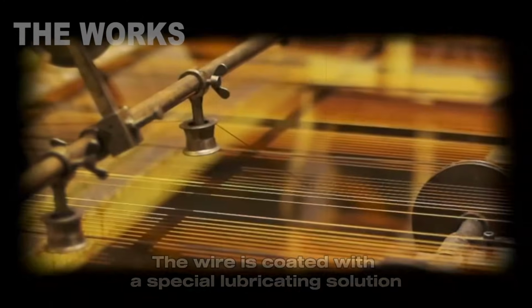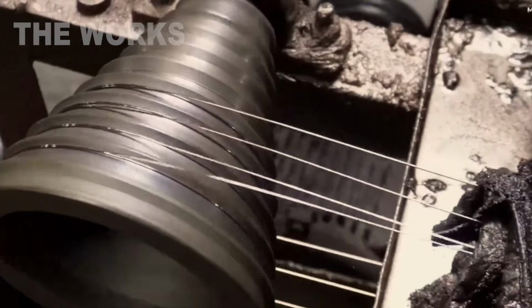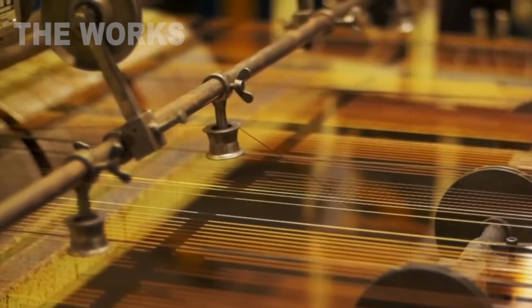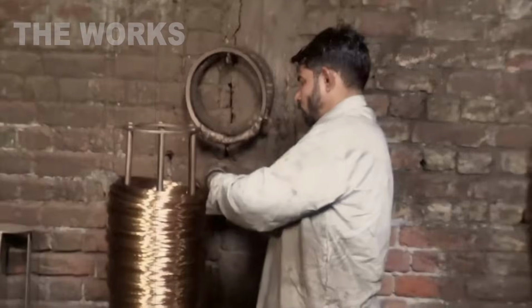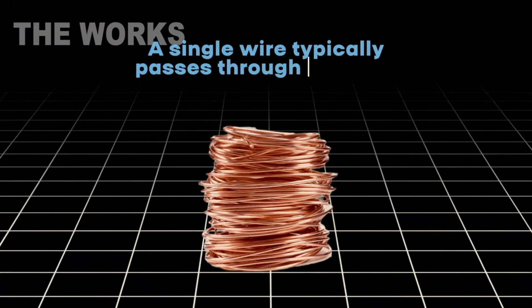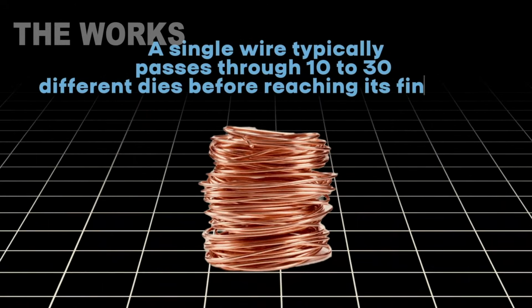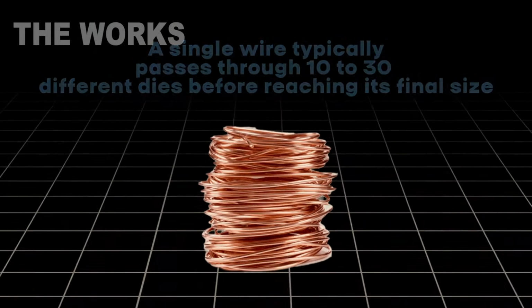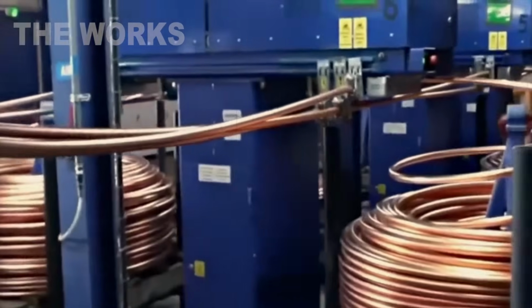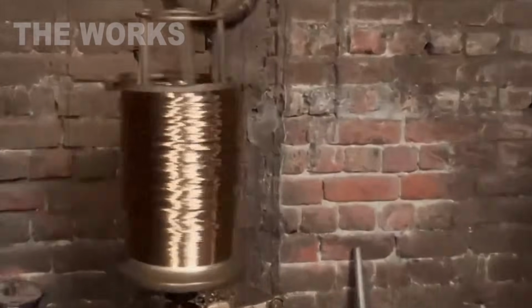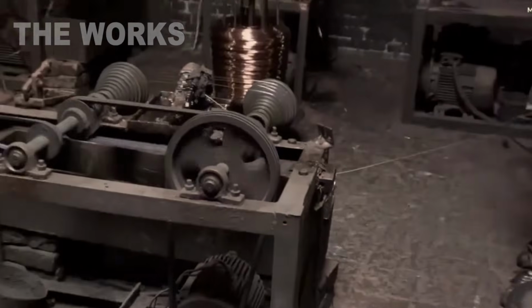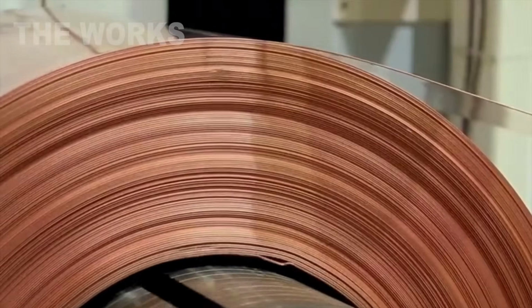A single wire typically passes through 10 to 30 different dies before reaching its final size. For example, from an initial diameter of about half an inch, the wire can be drawn down to around 0.08 inches, and even much smaller for electronic wires. As the copper is continuously stretched, its internal crystalline structure becomes harder and loses its natural ductility. For this reason, after a certain number of drawing passes, the wire must be lightly annealed at temperatures from 600 to 800 degrees Fahrenheit to soften the metal again.